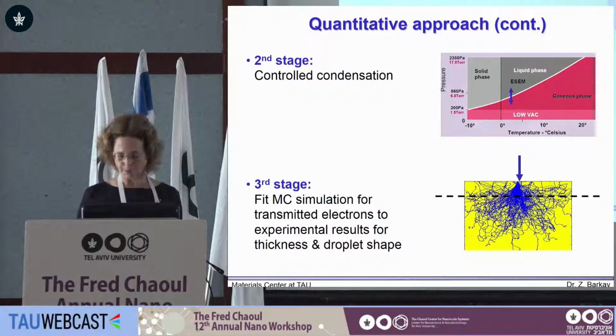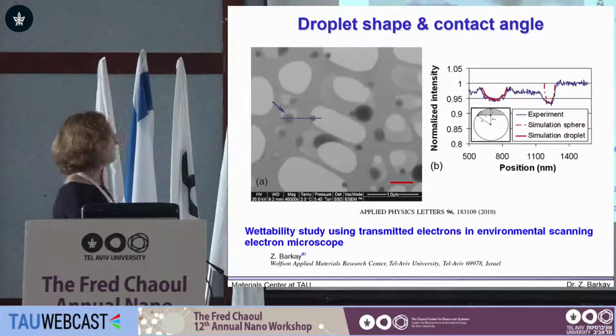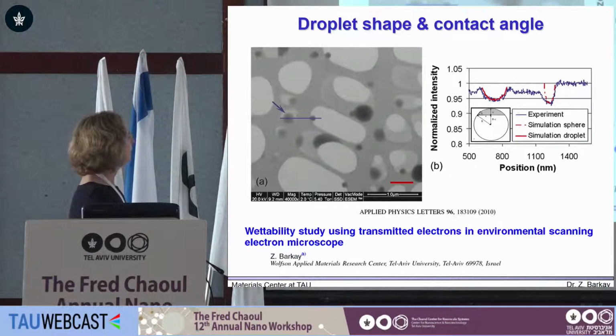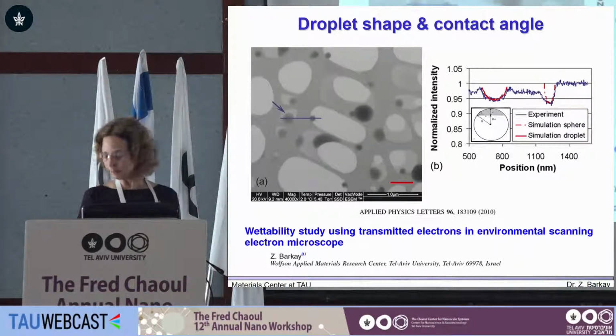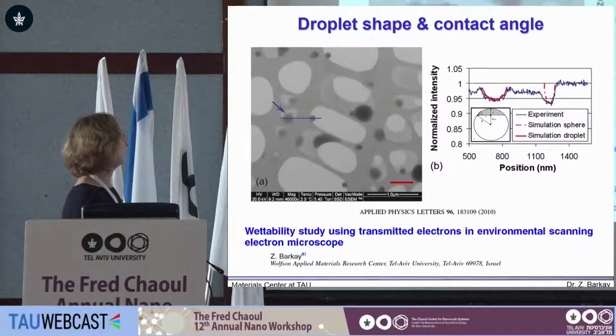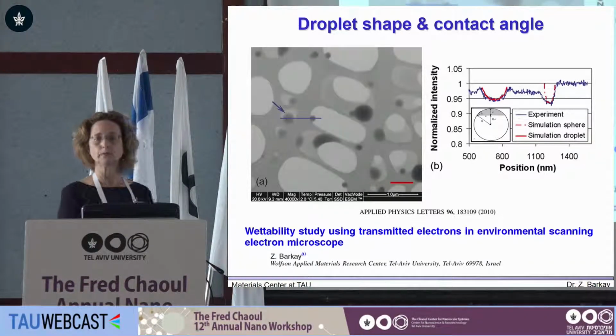Let's see how it works practically. This is an example of the holey carbon grid. You see here trapped liquid films, and on it some condensation of liquid droplets - so on the film, on the grid itself, on the liquid film. In this particular case, I added some polystyrene particles of 100 nanometers to form calibration.